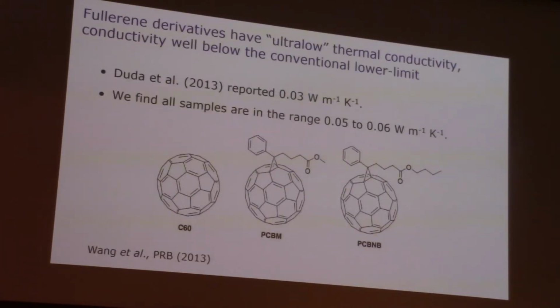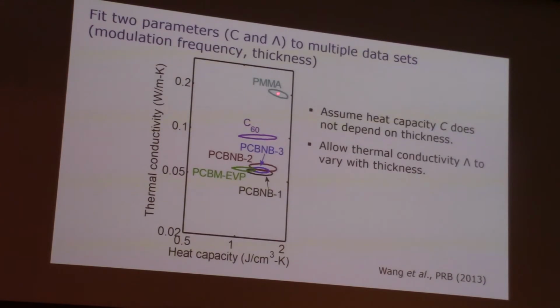And what's so curious about all this is that in some sense you might think this material should look something like the mixture of C60 with a polymer. That would be the effective medium way of thinking about the material. I mix a polymer and fullerene, and I get something in between. But if I mix a polymer and C60, I don't get in between. I get lower, and I get incredibly low. So this is again the lowest thermal conductivity of any dense material that we know about, created by that kind of mixing.